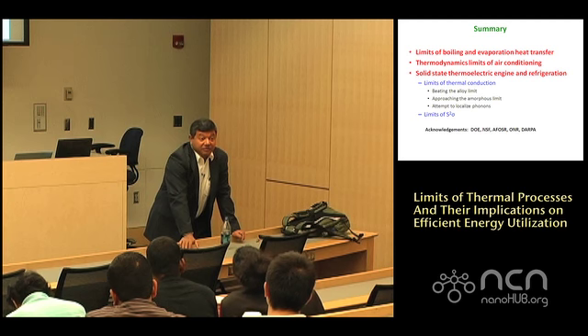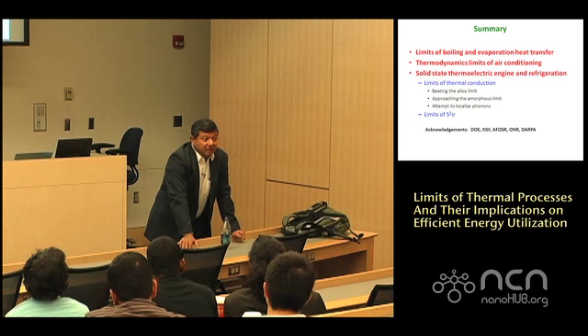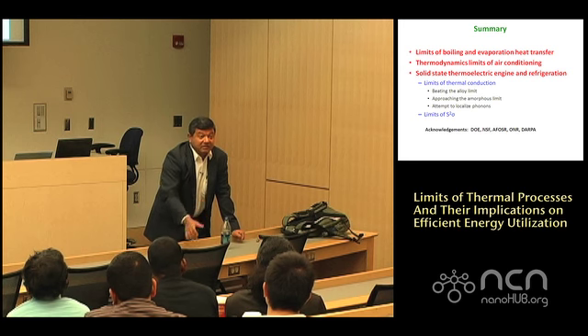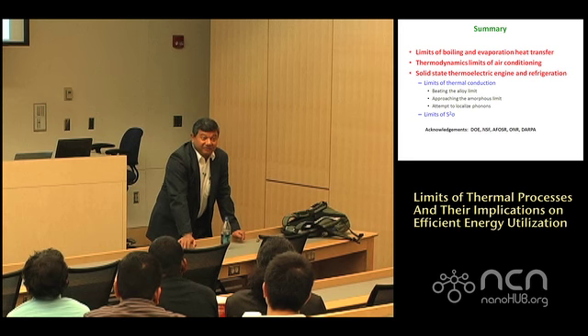But at the end of the day, you have to reduce the thermal conductivity below 1. That's the key, 1 watt per meter Kelvin. On the other hand, random materials are much easier to grow. And there's a practical aspect, the engineering side, of how to make these materials and use them. I mean, Gang Chen's approach of ball milling, Gang Chen and Zhifeng Ren and all, ball milling and making a bulk material out of nanostructures, that's great. I think that's the way to go.